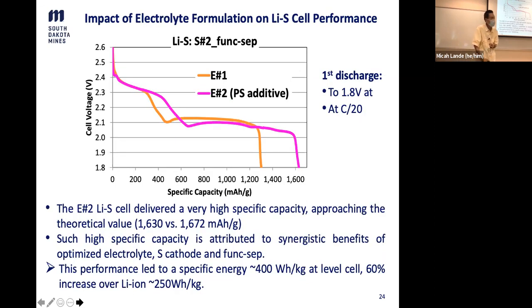Final example is that we show the impact of the electrolyte formulation on the cell performance. Remember we have two examples, one is E1 and another E2, and E2 has a polysulfide additive in it. When we compare them side by side, for this E2 cell you have further extended this high voltage plateau, and the low voltage plateau is also longer than the E1 cell.